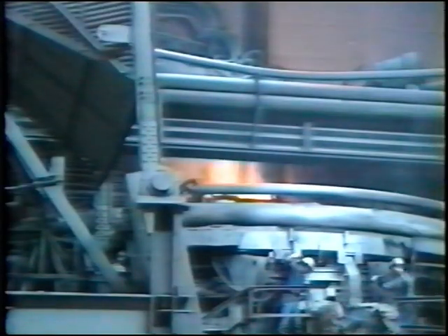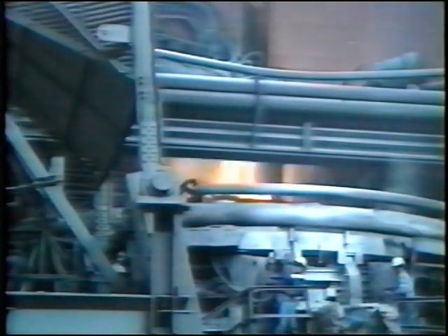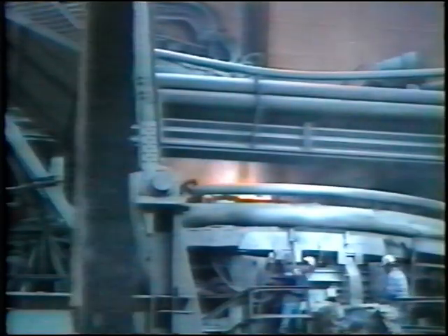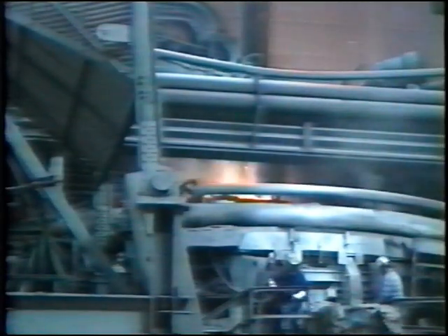3 massive carbon electrodes are lowered through the furnace roof and positioned above the charge. 85 million watts of electric power is activated, and the scrap is melted to a pouring temperature of 3,000 degrees Fahrenheit. Northwestern pioneered this ultra-high power method of steelmaking and has remained on the forefront of electric furnace technology since Paul Dillon defied the so-called experts a half-century ago.